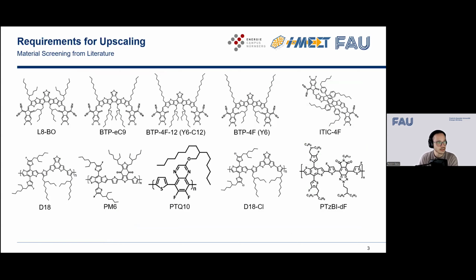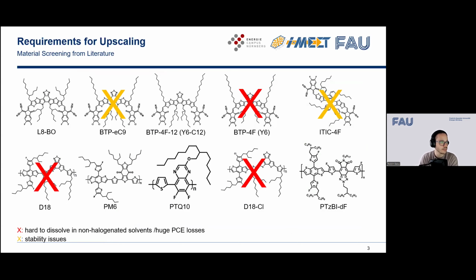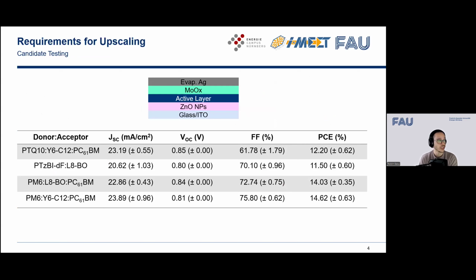With that said, we can already take out some of the materials that I suggested here, and some others were taken out because they usually, according to literature, lead to instability of our devices. With those candidates that we still have left, we tried a couple of devices. This is all 0.1 square centimeter cells with 100 nanometers of evaporated silver.